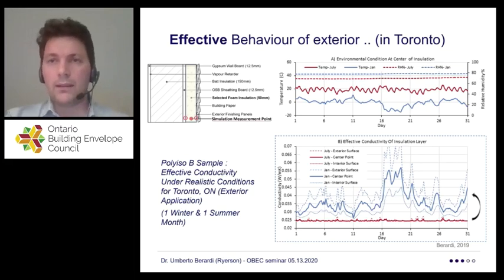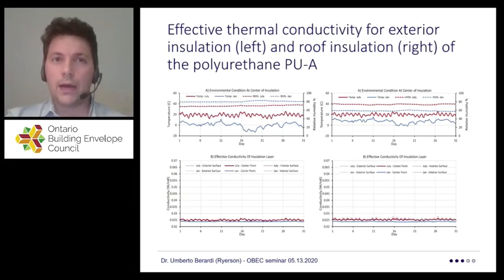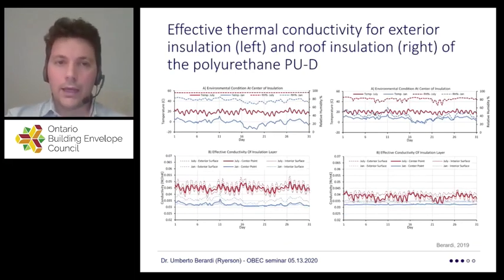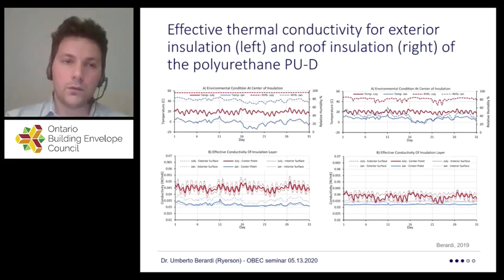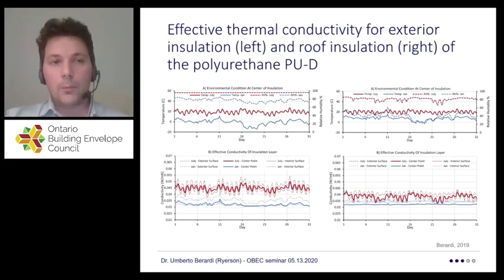And we've been doing this in many cities and some monitoring, not just with polyisocyanurate, but also with polyurethane, open cell, closed cell. You can see, for example, here the oscillation of the thermal conductivity as it goes up and down in the bottom line of these two figures. You see the continuous red line going up and down, oscillating around 0.045, but also getting sometimes values higher around 0.05, sometimes lower value around 0.04.